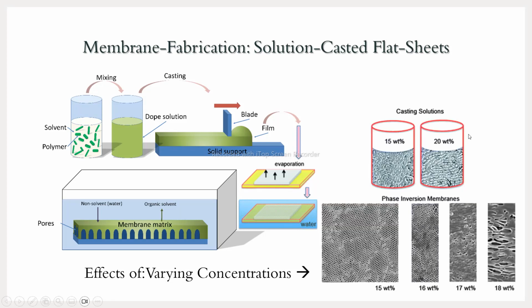Depending on varying concentration of the polymer inside the casting solution, the pore nature may vary. That means the number of pores, that is porosity, will decrease as we increase the concentration of the polymer inside the solvent. The homogeneity will decrease. In that way, the nature and number of the pores will vary depending on the concentration of the polymer inside the solvent.